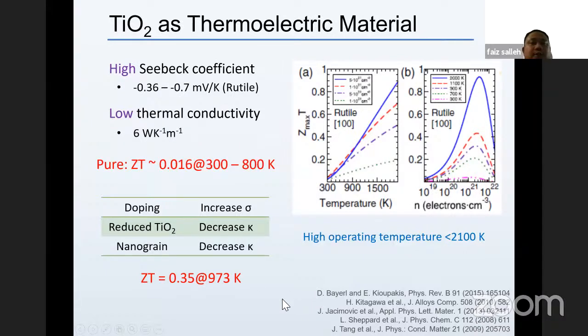So if we want to use this TiO2 material as a smart window material, yes, it has potential, but it has many challenges, and one of them is to improve its thermoelectric properties, especially at room temperature. Because if you want to use it for the smart window, it needs to be used at much lower temperature, around 300 to 400 Kelvin. If you want to use the window at a much higher temperature for some niche application, some niche space or some niche building, then we can have much better performance for that kind of application.